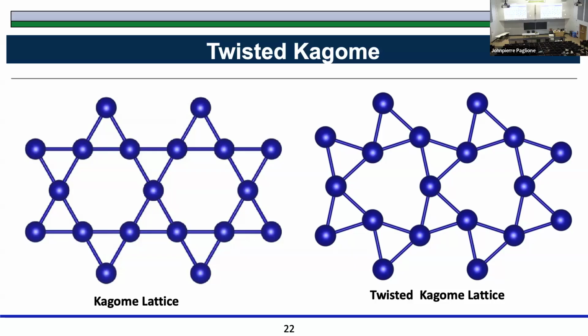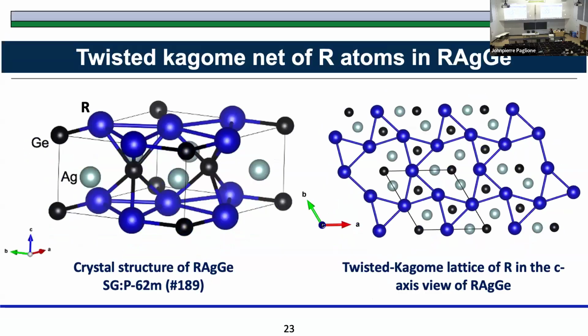And this twisting can generate some anisotropy within the plane. And you can play with that anisotropy, between some external parameters and the magnetism in the system, and you can maybe generate very interesting properties. I'll show you an example of that. I'll be very quick because of the time. So this is the structure of a material. The R is a rare earth, and then AgGe. There are hundreds of materials in this family again. And these blue atoms are the rare earth atoms. So here rare earths make the Kagome net, which is interesting in itself, but this makes a twisted Kagome net in the plane.